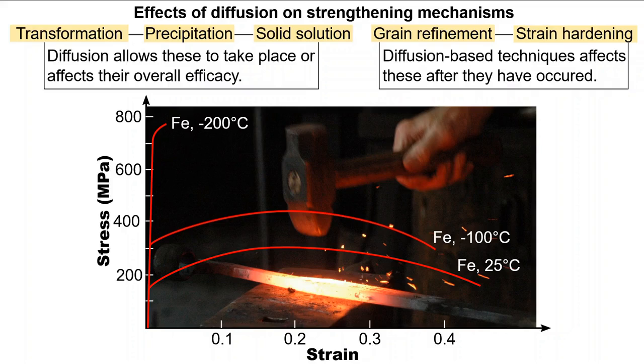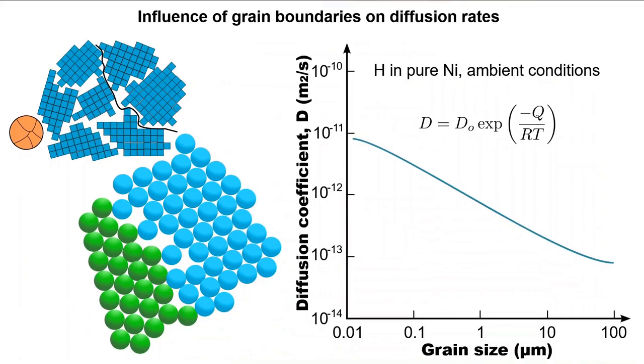We need to first start with what grain boundaries overall do to a metal from a diffusional sense. In part 1, it was presented that an increase in temperature dramatically increases the number of vacancies within a monolithic crystal. In the instance of a polycrystal, however, there are already an elevated number of vacancies occurring at grain boundaries. This is because there are inconsistencies in the packing between grains. This discontinuity and the limited number of packing orientations, as per the crystal type, can create a wide range of free volume in a polycrystal.